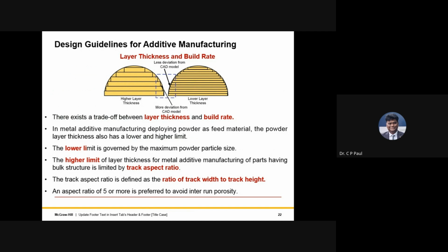The layer thickness and the build rate is the second thing that we need to focus on. If you have a higher layer thickness, then there would be stair stepping effect coming in. Though the build rates are good, removing the stair stepping effect will also cause extra post processing time. Then we have to really optimize how to take care of the stair stepping or go for the lower layer thickness. So that's the way people decide and define on this.